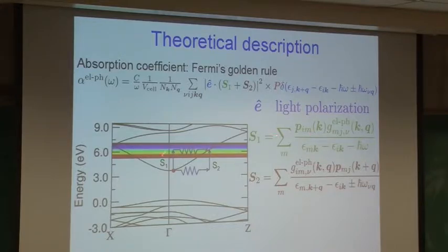If you look at this formulation, you see exactly the same thing happening. You have a dipole matrix element that signifies your absorption to the virtual state. Then you couple your electron to a phonon with the electron-phonon coupling matrix elements, which are given here, which will bring you from k to k plus q, which is your final state. But of course, you can also do the opposite process. You can first scatter with a phonon to a virtual state, and then from the virtual state, absorb a photon to end up in your final unoccupied state.